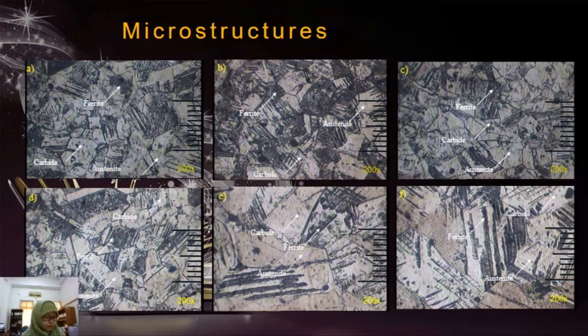The result of this research is, first, the microstructure. The microstructure test result shows that the FeCrMn alloy had an austenitic structure with a little ferrite in the austenitic matrix. The austenite structure with clear grain boundaries looks bright, while the ferrite structure looks darker. The high content of manganese element encourages the formation of a stable austenite structure. In contrast, a large amount of Cr element as a ferrite stabilizer causes a ferrite structure to remain. Carbide deposits are seen among the austenitic structures, which have relatively homogeneous grain size.